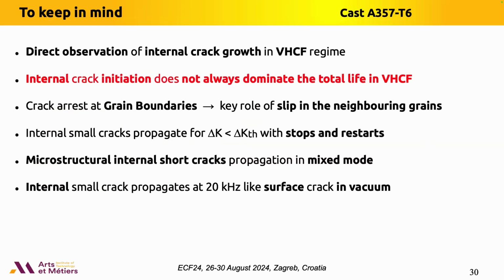So to conclude this first part, we can see that in situ synchrotron ultrasonic fatigue tests are very useful to obtain a direct observation of the internal cracks. It shows that the internal crack initiation does not dominate the total life of the specimen in the very high cycle fatigue regime, and the crack may be arrested at the grain boundary. That's why there is a very important role of the slip system of the neighboring grain around the crack.